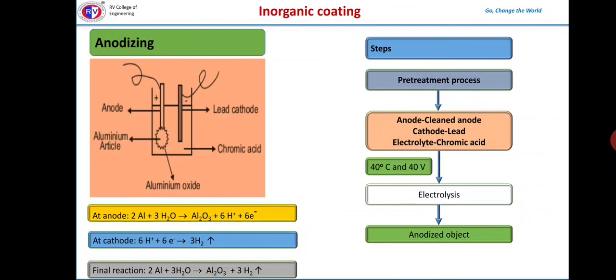The thickness of the deposit is controlled by adjusting the current and the bath solution. The coating is still slightly porous and it is sealed by dipping in hot water. Al2O3 gets hydrated to Al2O3·H2O which occupies more volume and hence protects the metal from corrosion.